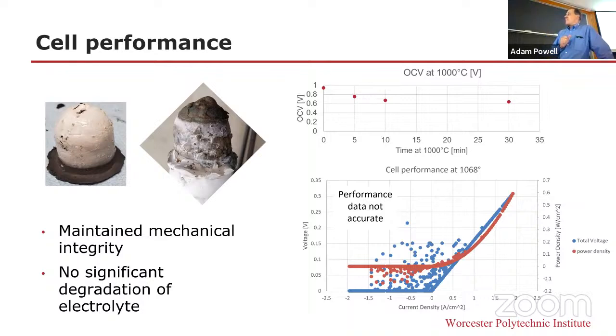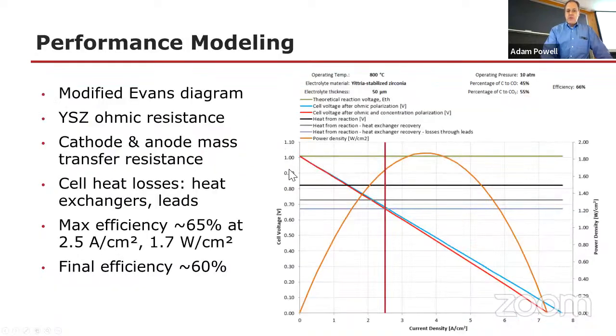accurately, unfortunately. And then he finished, and we've had, well, we just leave it at that. But the open circuit voltage that he measured is very close to the theoretical open circuit voltage. Carbon is one of those things where in C plus O2 to CO2, the entropy is very close to zero. So the free energy and the enthalpy are very close to each other. And so we get a voltage versus current density prediction that looks like this. It declines as you increase the current density because the resistance losses are proportional to the current density. So you start from your theoretical and decline from there.